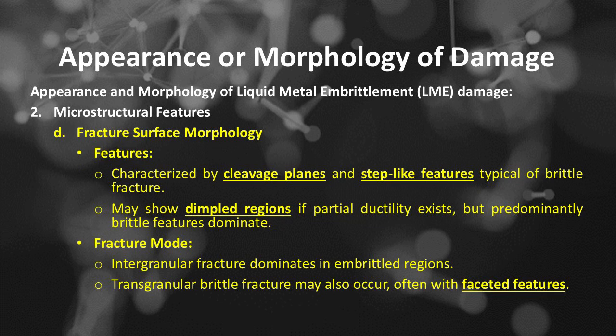Microstructural features, number D: fracture surface morphology. The features of fracture surface morphology include: characterized by cleavage planes and step-like features typical of brittle fracture, and may show dimpled regions if partial ductility exists, but predominantly brittle features dominate. Fracture mode of fracture surface morphology includes: intergranular fracture dominates in embrittled regions. Transgranular brittle fracture may also occur, often with faceted features.